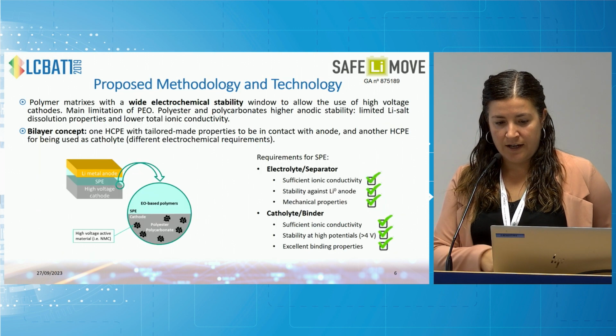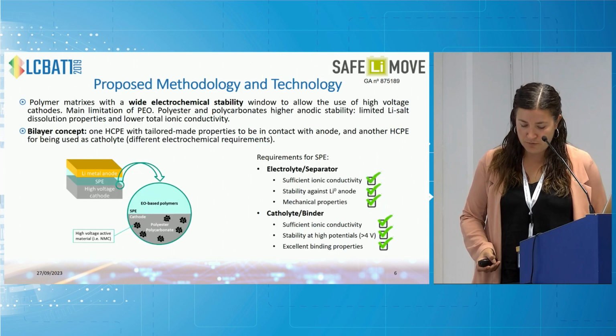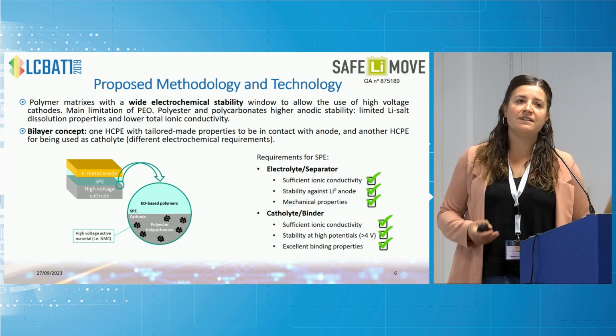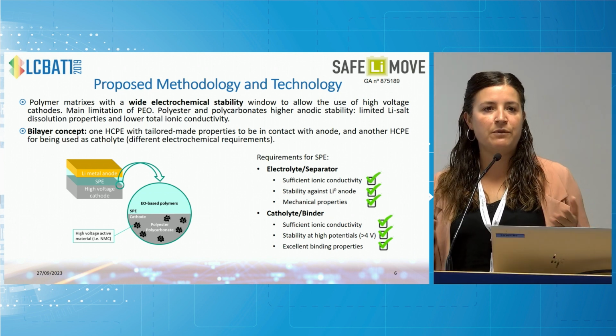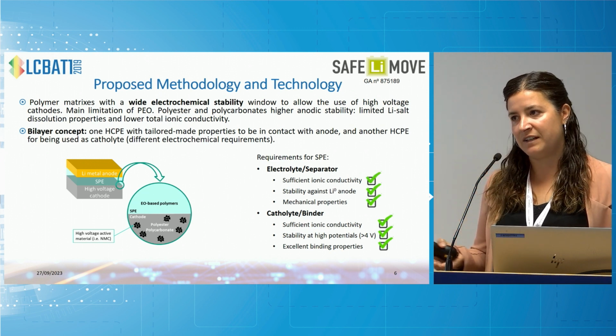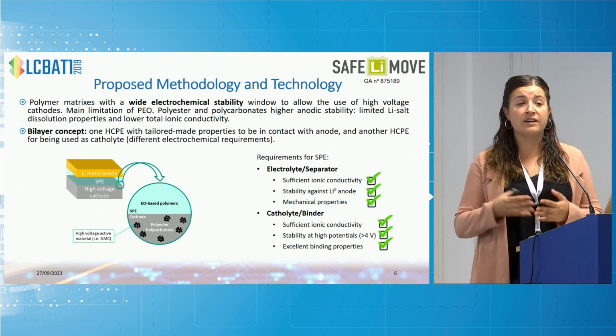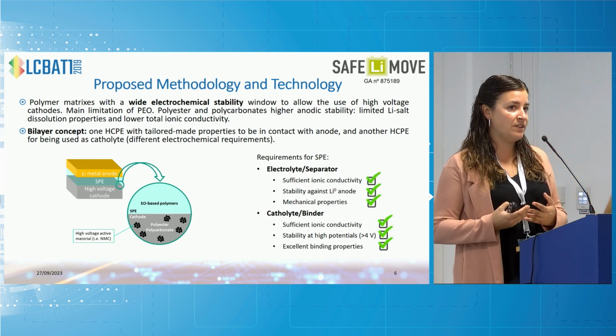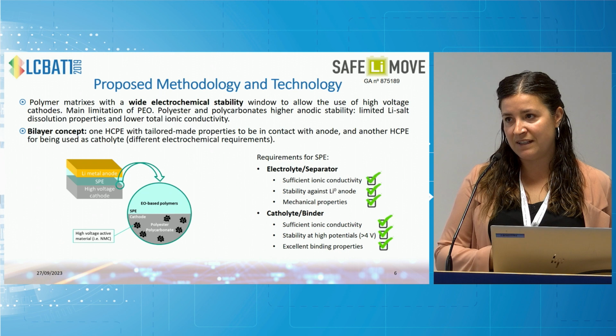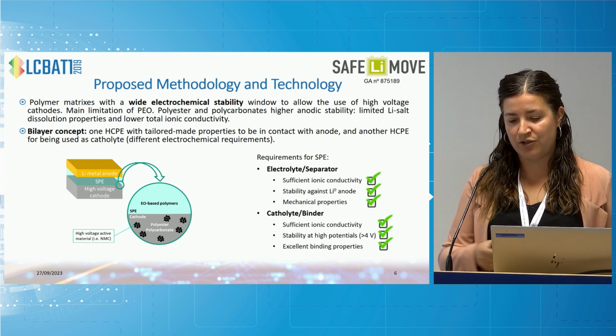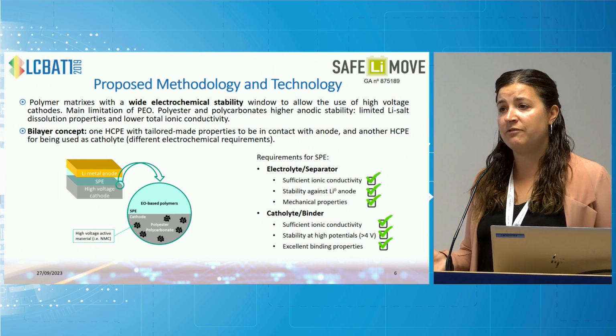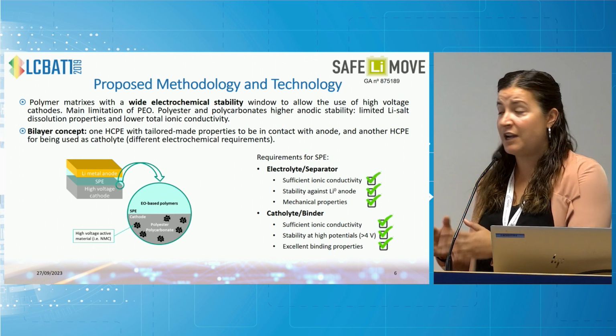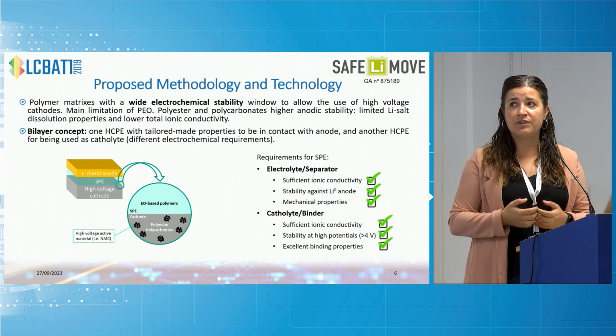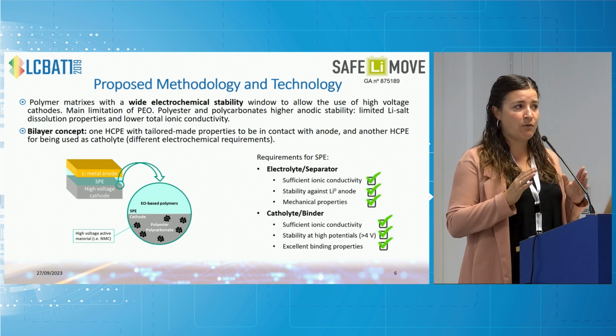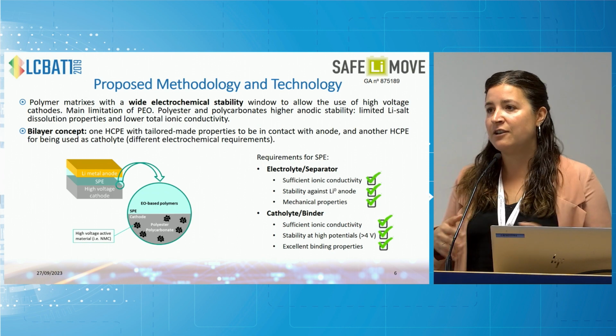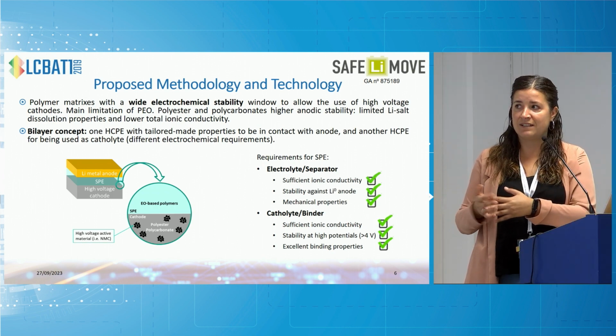And then, in order to design the technology that we were looking for by means of the electrolyte, we started to consider that different environments in the cell require different types of materials. So if we are thinking of the cathode side, we really need to have a high voltage stability, while if we consider the lithium metal side, we really need to have a stable SEI formation. So we realized that it was not going to be easy to handle both sides with the same type of hybrid electrolyte. So for that reason, we developed a bi-layer concept where we wanted to have one type of chemistry in contact with the lithium metal and another type of chemistry within the cathode, used as catholyte.